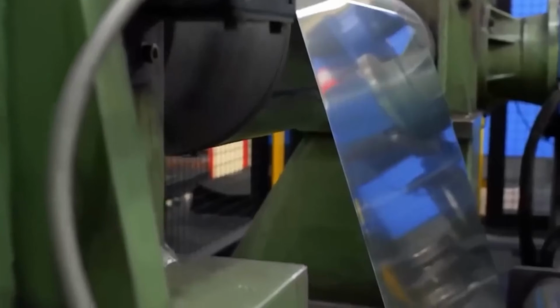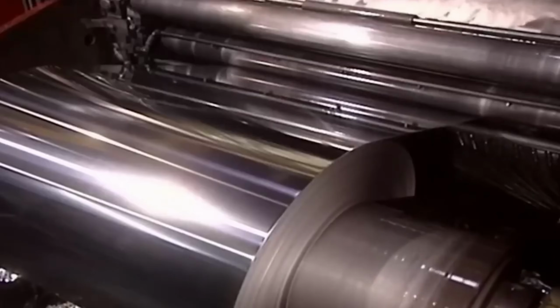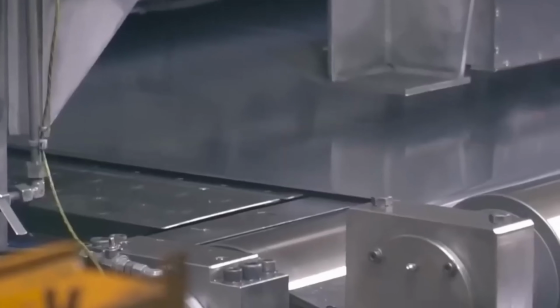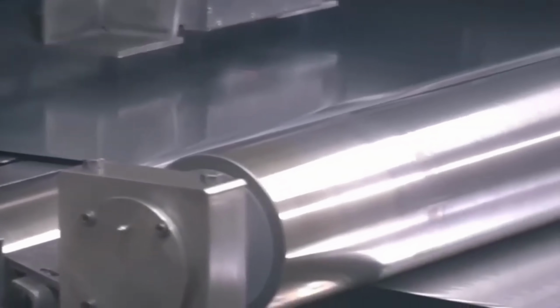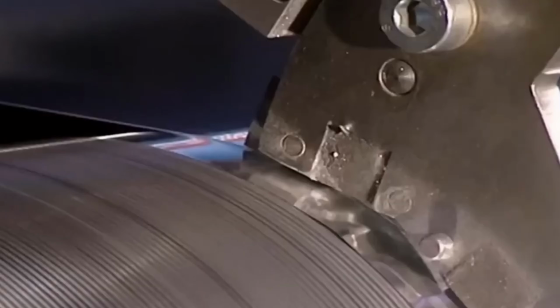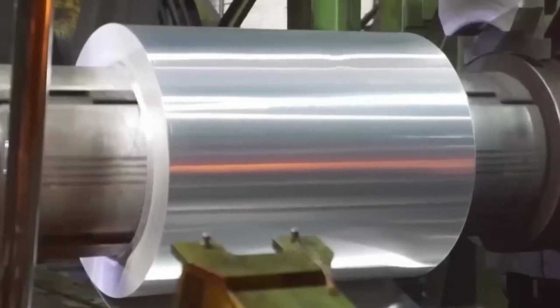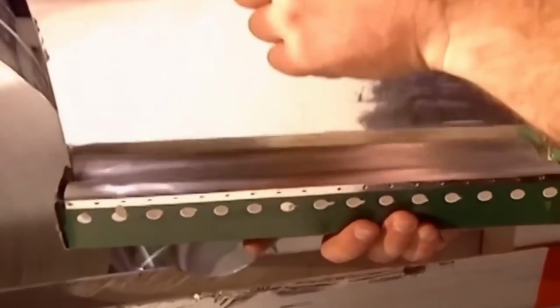But aluminum foil requires an even thinner result, often between 6 and 25 microns, thinner than a human hair. Rolling metal this thin in a single pass would damage the sheet, so manufacturers use a technique called double rolling. 2 layers of aluminum strip are stacked together and rolled simultaneously. This allows the mill to push thickness even lower without tearing the metal. Double rolling creates a unique characteristic of foil. One side shiny, one side matte.